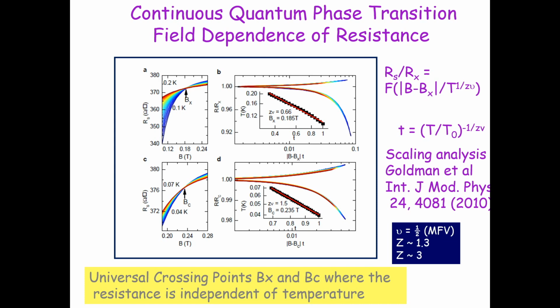Now we can do a scaling analysis of these data. This is the standard scaling ansatz. If I plot my sheet resistance as a function of magnetic field at different isotherms, where temperature is constant, it turns out that all of them cross through this critical field Bx. This is the normal side, this is the superconducting side, and I can do a data collapse for this as well as this. So this is the superconducting side and this is above the transition.